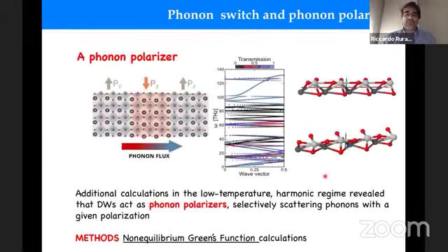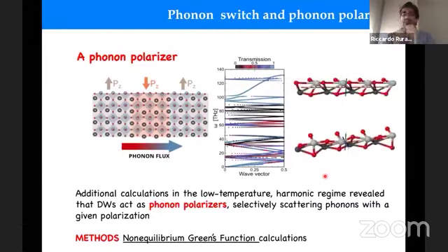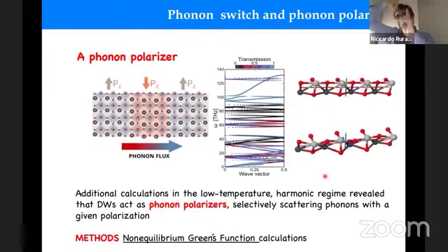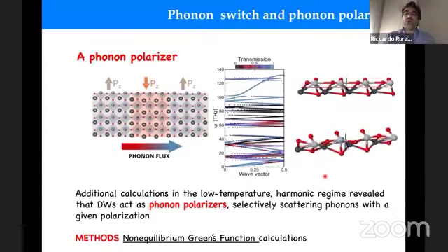And finally, about this topic related with domain walls, we looked even closer, and we could see that these domain walls are not democratic scatterers. They like to scatter especially some kinds of phonons. So phonons like this one that vibrate perpendicular to the interface go through the interface almost unperturbed, while phonons where the vibration is parallel to the interface, which is exactly where you create the defect, your boundary, these are the ones that are scattered.